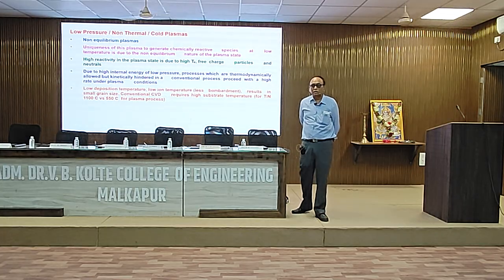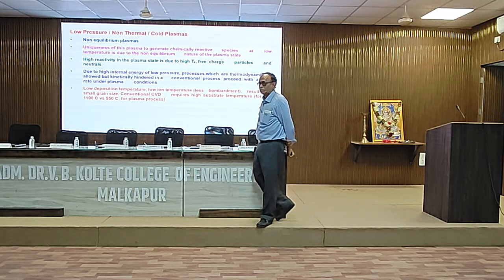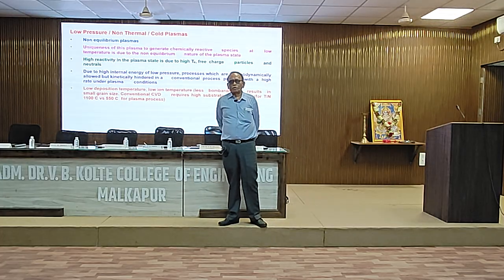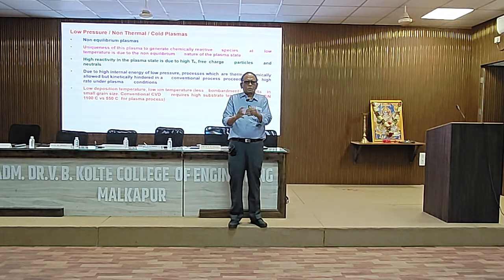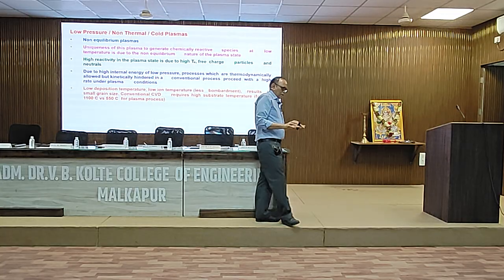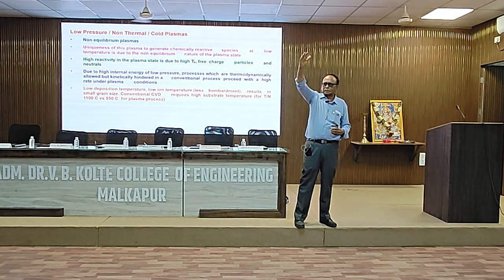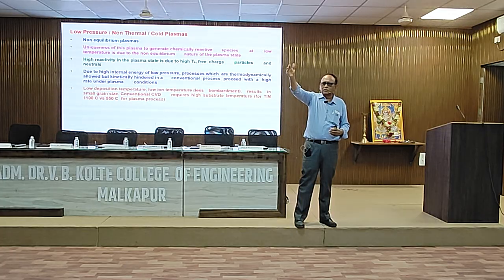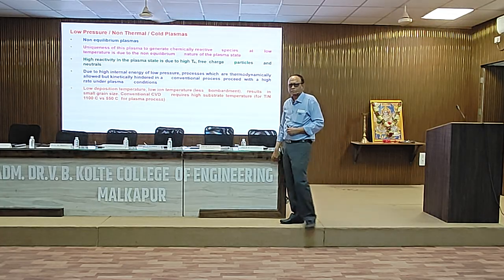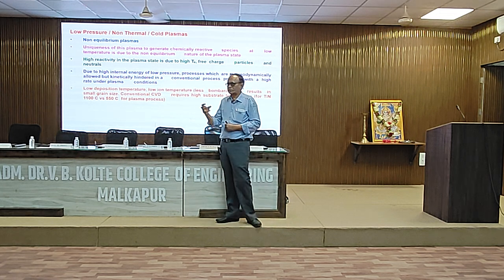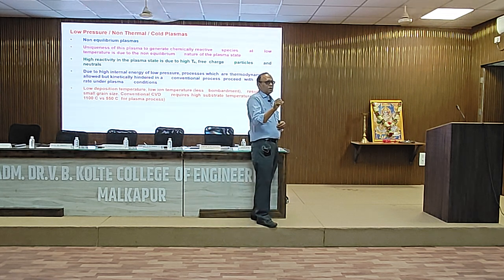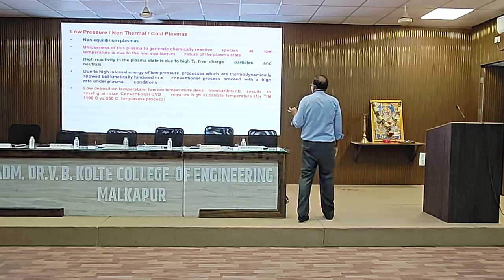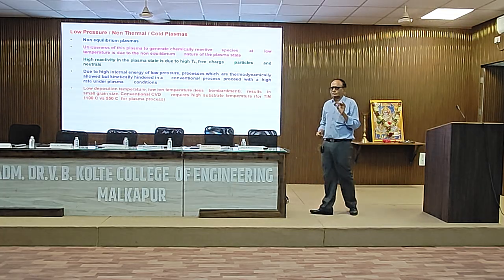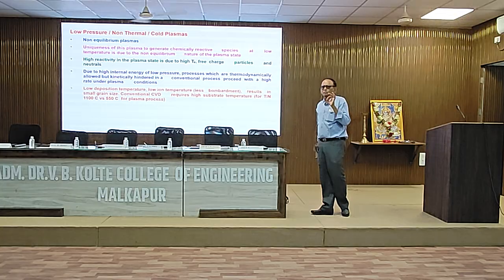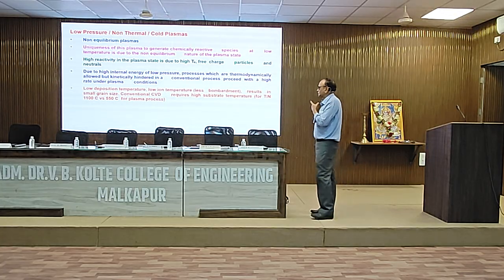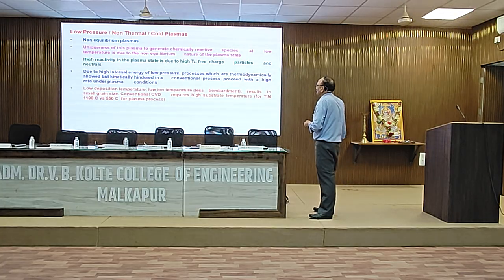Now this is a very big gain in terms of your industrial production, because if you are using tool steel, which has been given some treatment, and if you are taking a temperature of 1100 degrees centigrade, then you are basically tampering with the microstructure of the steel. So if you have derived some advantages because of microstructure modification, the steel will get annealed out and you will lose those advantages. So it is always desirable that you should have lower deposition temperatures, and that is possible using this plasma. So I have just shown you one example.